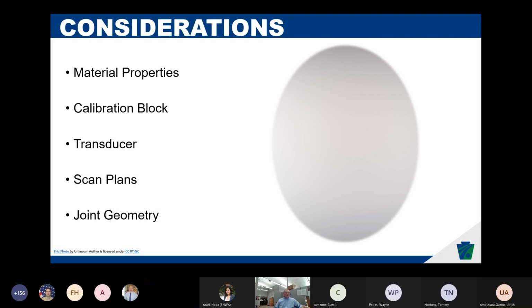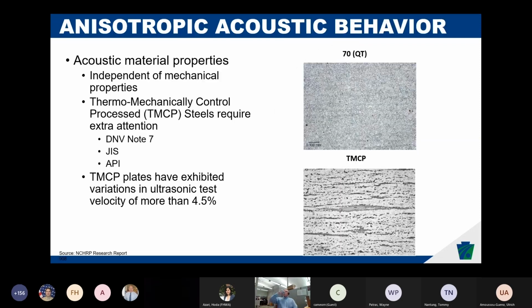So material properties have a significant influence over the test method. So the calibration block, transducers, scan plans, joint geometry, it's all things that need to be considered before you just implement phased array ultrasonic testing. Starting with material properties. There's this anisotropic acoustic behavior that happens with some certain steels. And it really relates to texture of the steel.